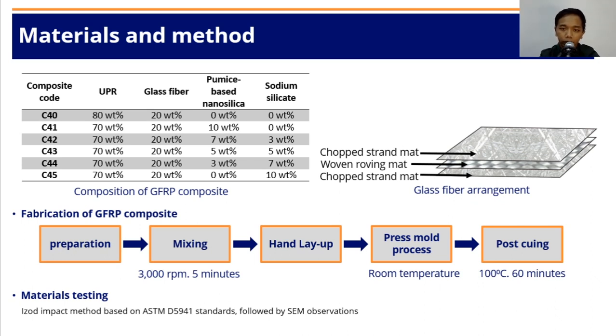After the process is complete, post curing is executed at 100 degrees Celsius for 60 minutes. After completion of the fabrication process, the GFRP composite were prepared with dimensions of length, width, and thickness, respectively 64, 13, and 3 mm, 7 pieces per variant for impact testing, which would be executed using the impact Izod method. After that, the SEM observation process was carried out on samples that had gone through impact testing to analyze the structure of the GFRP composite.